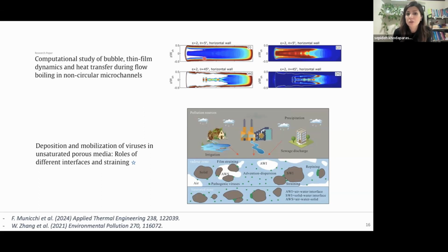And you see that the zones where dry out is happening, this is the corresponding heat transfer coefficient, Nusselt number, I believe. The regions where you have these dry out patches suddenly have very low heat transfer compared to the rest of the regions where you have the thin film. And these are the contact angles, basically the wetting condition on the channel. If you increase the contact angle, going from a more wetting to a less wetting channel, you see that in the same exact condition, these zones are expanded and you have much lower heat transfer. So in these kinds of scenarios, it is directly translatable to what I was talking about.